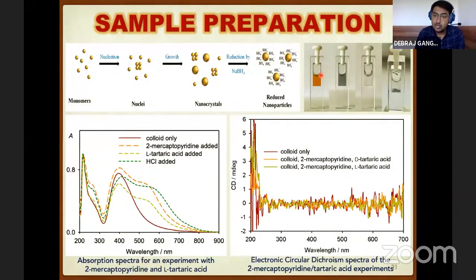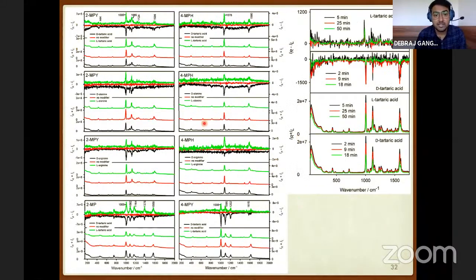It's almost zero signal in circular dichroism. That is, the solution as a whole is not chiral. Chirality is present only on the surface, I mean where the analyte is attached to the silver surface. It's a surface phenomenon. That's why the solution as a whole is not chiral. But when we record the surface enhanced Raman optical activity spectra, we get mirror image spectra for the 2 enantiomers. You see the Raman spectrum has intensity in 10⁸, and this has intensity in 10⁵. So the CID ratio is 10⁻³, which is quite high.